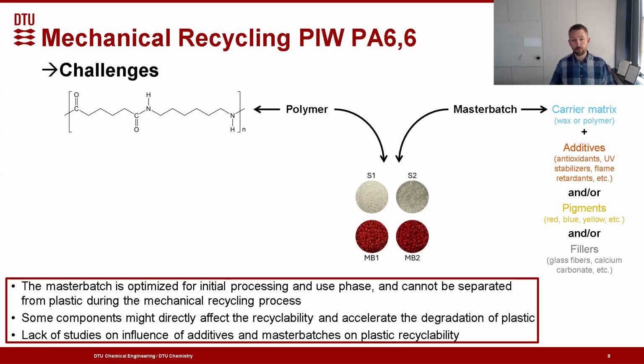In addition to this, we also have pigments, different colors. There can also be fillers and other things in these systems. So generally in the industry, you would be combining a base resin that could come from a range of different suppliers with master batches that could also sometimes come from a number of different suppliers. These systems are optimized for the first and initial phase of the use, so the initial processing. And once we've mixed them together, it's not possible to get the low molecular weight compounds out and obtain the pure resin again. You will always have this mixture.